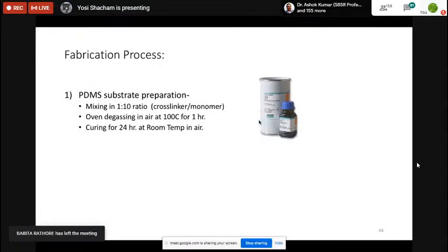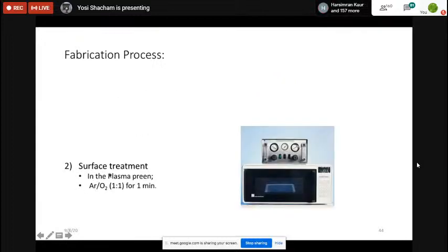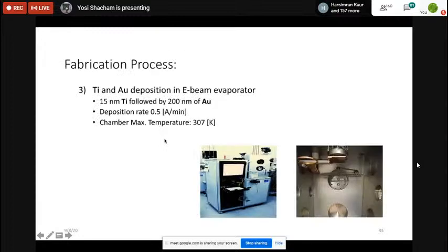I'll go quickly. First, we take the PDMS. PDMS is a polymer, an elastomer. This is not going to be a class in material science, but the way to make this polymer is you buy the cross-linker, you buy the monomer, you mix them together, wait 24 hours, and you have the polymer. So we can control the composition. For example, 1 to 10 is very much used, but the reason I'm showing you this slide is that we can control the mechanical properties of the polymer. And this is going to be a big, big issue. Next, we clean the surface with oxygen plasma. Next, we put titanium and gold on top of it. This is our new evaporator.